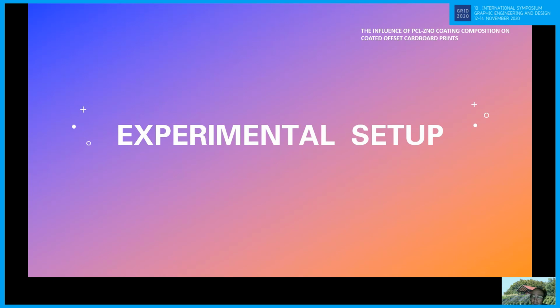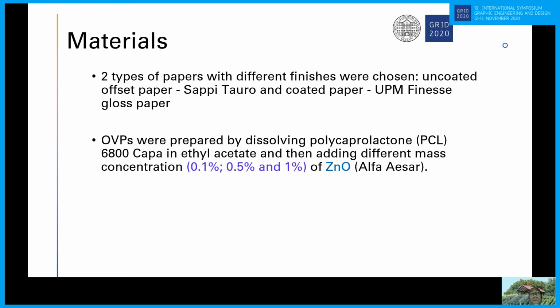So for the conduction of this research, we chose two materials. One was uncoated offset paper. Both papers were 300 grams per square meter. The uncoated paper's finish doesn't close the surface so much, so this paper is more absorbent, and the coated paper, which had a gloss finish, was the other one.